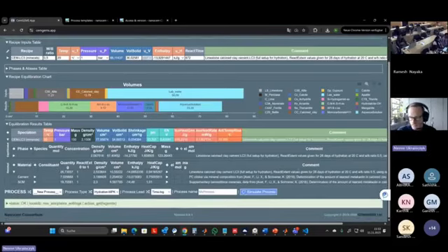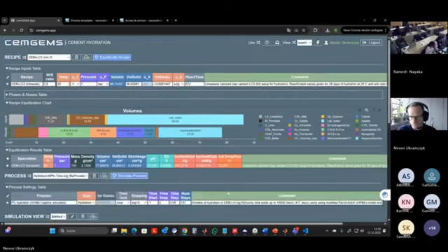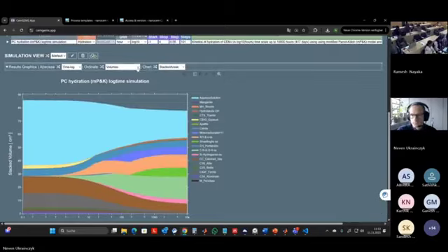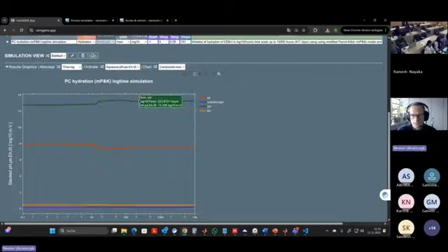Simulate process. We can see the pH increasing because of the alkalis releasing, and then decreasing because of pozzolanic reaction, probably. Maximum 13.35.